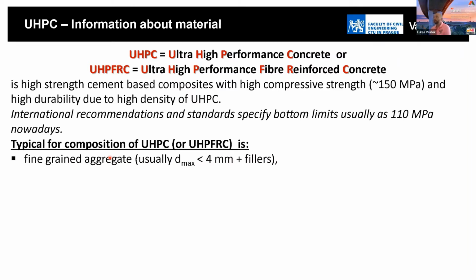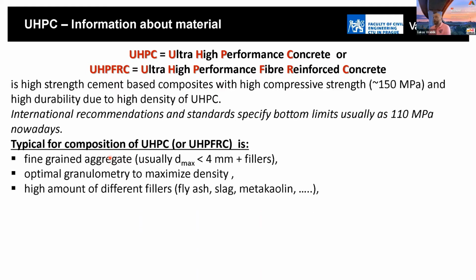The typical composition of UHPC is fine-grained aggregate. Usually, the maximum diameter of the aggregate is less than 4 millimeters, plus a lot of fillers. We use optimal granulometry. The reason is to maximize the density of the concrete mass and the density of the concrete volume. Also, we use a high amount of different fillers, especially fly ash, slag, and metakaolin. The reason is to improve the characteristics due to the compacting of the concrete and to increase the possibilities of realizing different shapes of the concrete elements.